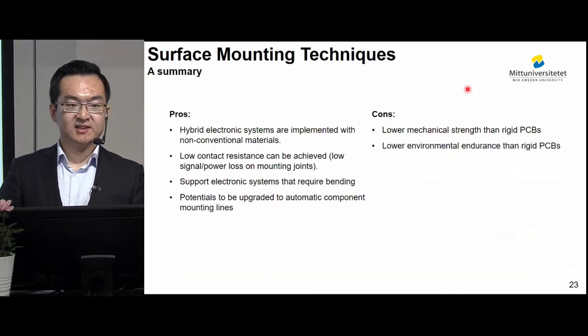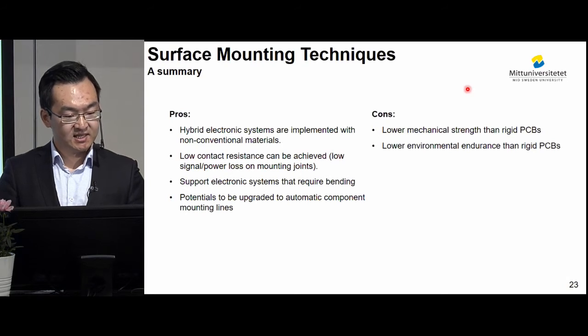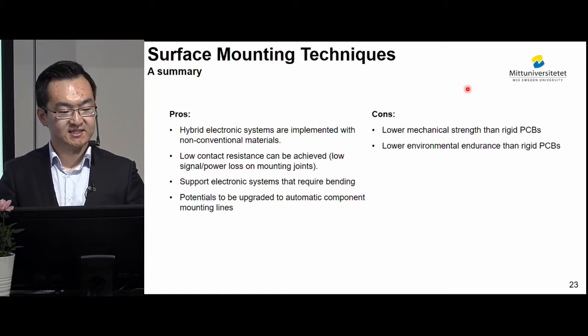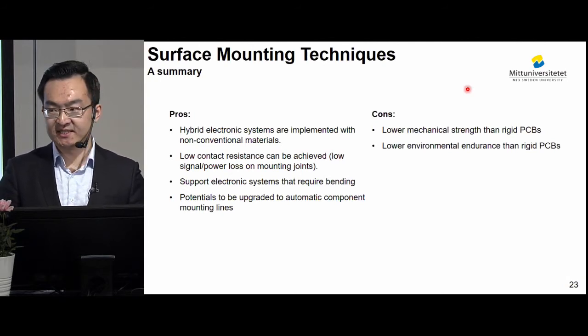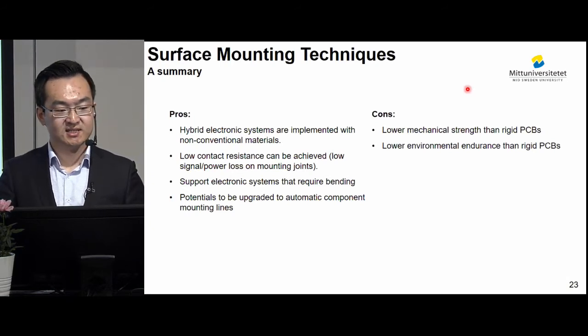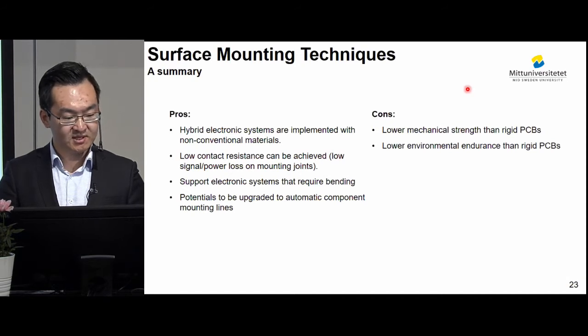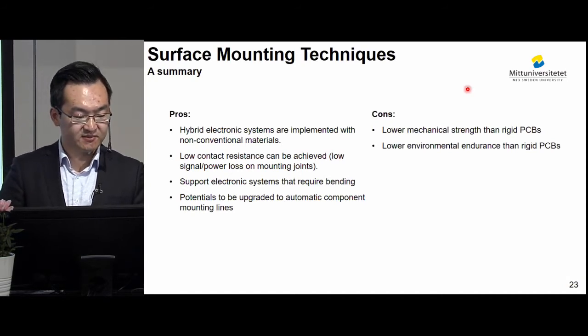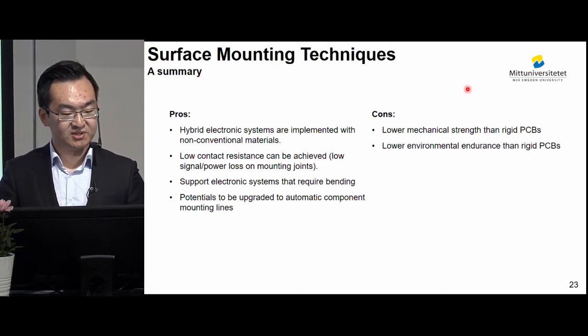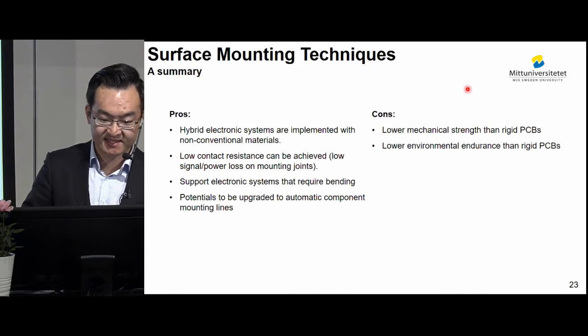And I would like to give a summary of the surface mounting techniques that we have developed. The advantages of these techniques are that it has proven that hybrid electronic systems can be implemented with non-conventional materials, and low contact resistance can be achieved, which means we have a low signal or power loss on mounting joints. The result also showed that some of the surface mounting techniques support electronic systems that require bending. And for the low temperature solder paste method and for the isotropic conductive adhesive method, we can upgrade them to a fully automatic mounting process with the necessary equipment provided.